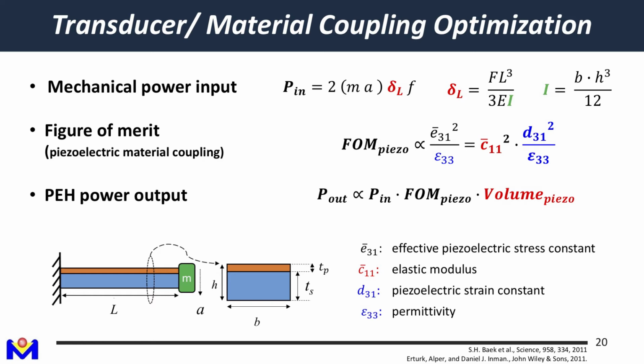Like I just mentioned, you can try 3-3 mode because of the higher dielectric constant. But in general, it's not easy. You also have to consider the microfabrication, and also the effective volume. As I just mentioned, for 3-1 mode it's quite intuitive: you can have a single beam, a single piezoelectric film, and a thinner substrate. For 3-3 mode, of course, you can have the same thin beam, but you still have to remember that if you only have a top electrode, you cannot retrieve the electric field in lower positions, so it's not really effective.